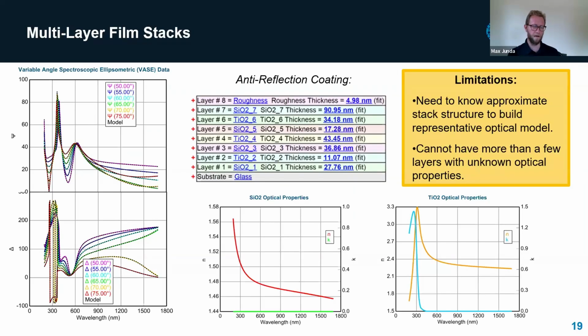So the last case I'm going to cover here is the case of multi-layer film stacks. All the examples I showed before were for single films that were deposited on a substrate. In this case, this is an anti-reflection coating that we measured is deposited on glass, and it has a large number of films, 7 different layers present. And so on the left, we're showing the raw data and then the model fit. And you can see we're actually able to fit the shape quite well.